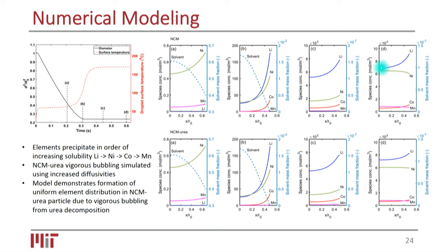However, for the neat NCM particle, we do see a profile in the element distribution, right? So it's not a uniform distribution. That explains why we need a relatively long time for the calcination step to smooth out the distribution. Whereas by adding urea, although we still see a distribution, that is due to the fact that we do have different ratios for the elements, the profile in the radial direction seems to have a more uniform distribution. And that is what urea is doing to the system.